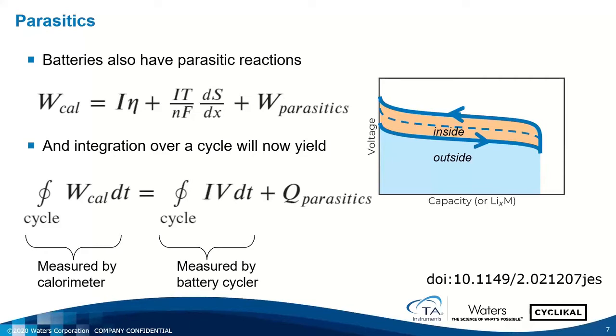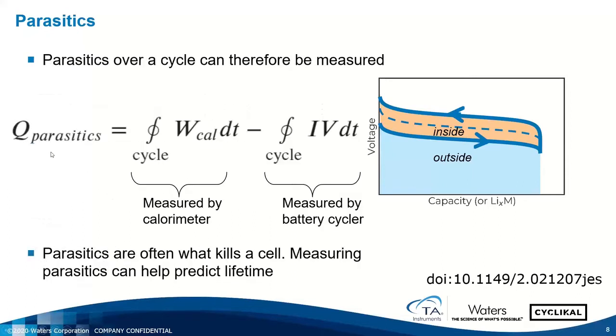So now, if we reconsider what we actually measure, we would have the heat measured by the calorimeter integrated over a cycle. We'd have the overpotential heat measured by the cycler, and then we have this extra term, and this corresponds to the parasitics. And so rearranging this equation, we now have a method for measuring the parasitics of the cell. So if I cycle my cell and I measure the heat from the calorimeter, and while I'm measuring the heat from the calorimeter, I also look at my current and voltage from my cycler, I can integrate these, subtract them, and what's left over is my parasitics.